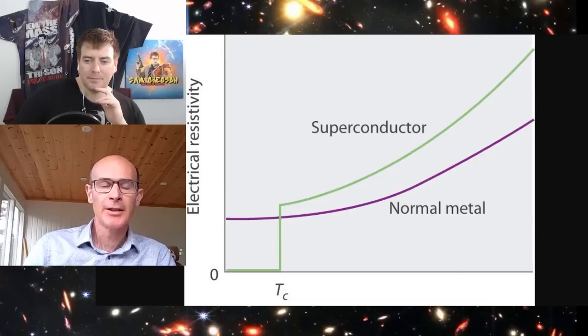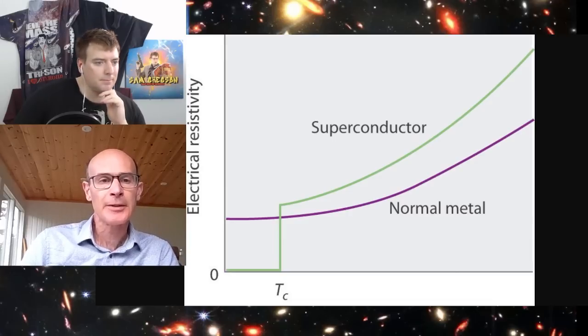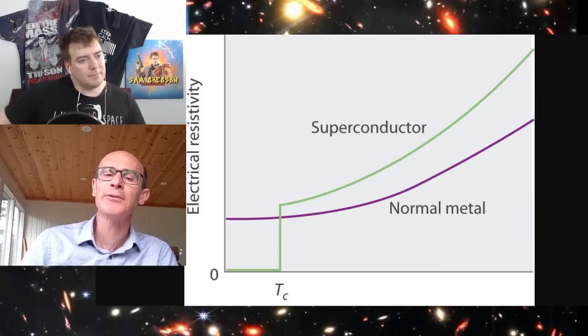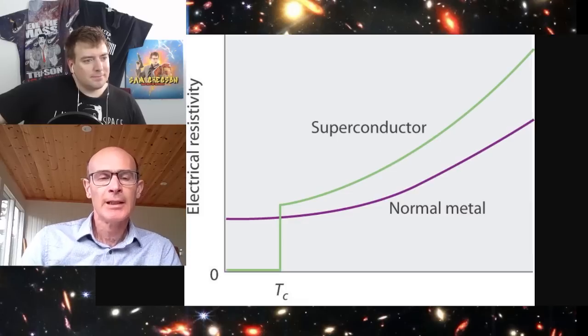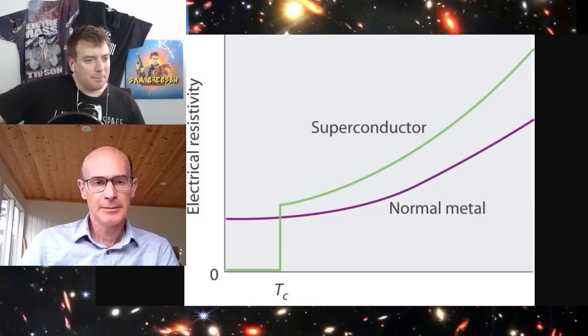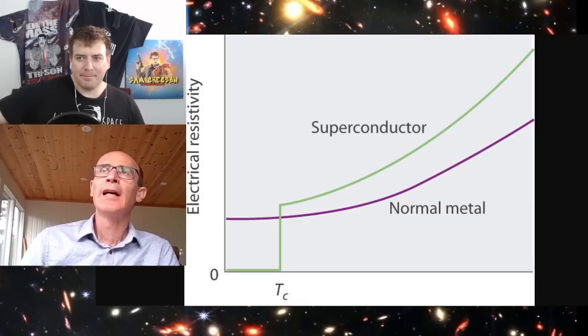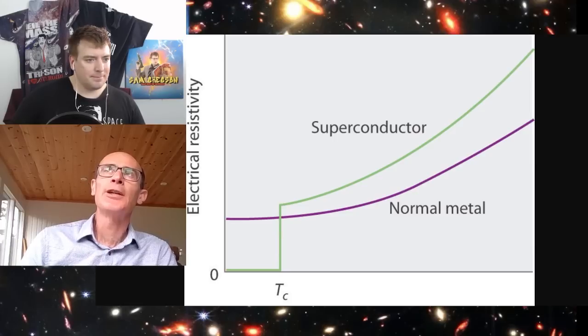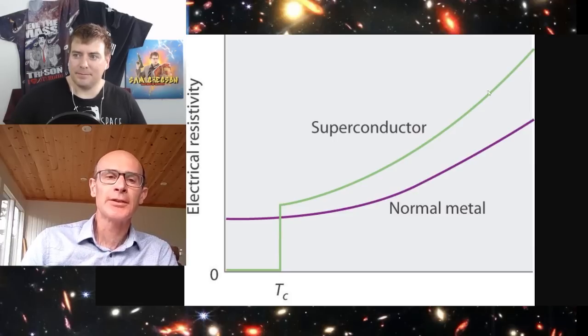The next thing you would do is leave the field switched on, and you would cool the sample again through the transition temperature back to low temperatures. What will happen then is that in the normal state, when you've got the magnetic field applied, the magnetic flux will penetrate the material. And when you cool through the superconducting transition for most superconductors, there will be incomplete repulsion of the...